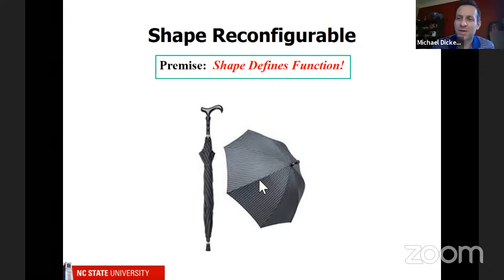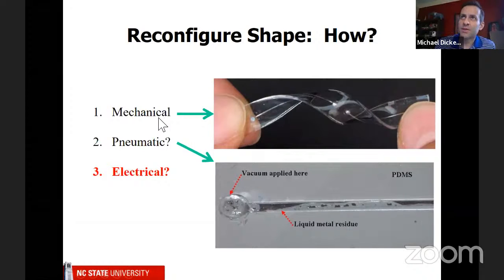Okay, so how are we going to do this? One way is to use mechanical forces, and I showed you that on Monday, where you can stretch it inside of an elastomer. Another way you might do it, and as a chemical engineer this is the way I would probably choose, is to pump it. But the problem is that in one of these microchannels, the liquid metal tends to stick to the microchannel walls. Because of this oxide layer, it's very sticky to most surfaces, so you can't just pump it and move it back out. It's kind of like wet paint. So we would really like to do this electrically, because if you can do it electrically, you have better control over it anyway. So that's kind of exciting.